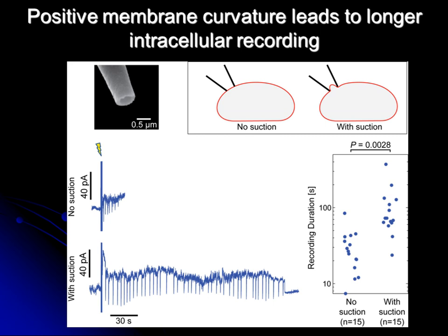So we did an experiment to prove this hypothesis. We have a glass pipette, and then we place the pipette just in contact with the cell membrane with no suction. Then this piece of membrane is rather flat. Then we apply the electroporation pulse and measure how long it takes for the pore to seal. In another case, we put a gentle pressure through the glass pipette. It will curve the cell membrane with the suction force. In this case, we also apply the electroporation pulse and then measure how long it takes for the pore to seal. Indeed, we found that the membrane pore seals much slower when you apply suction compared with when there is no suction. And this proves that the positive membrane curvature is what leads to the longer intracellular recording.